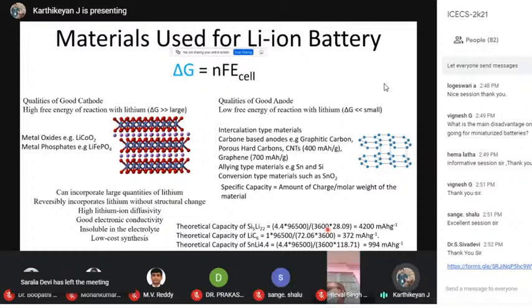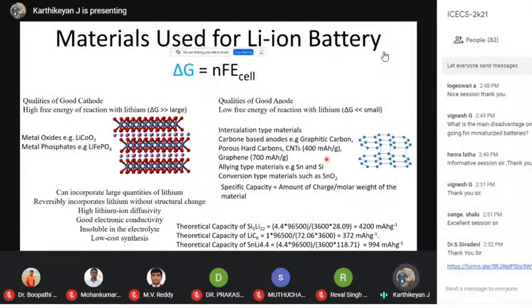Similar to silicon, we can also have tin. That is also an alloy material, but the problem with tin is again pulverization effects as well as poor interparticle connectivity. And what about other forms of carbon? Yes, carbon has other forms, like carbon nanotubes, and these carbon nanotubes have a better capacity than graphite, but again, it is not up to silicon or tin, right? Graphene has 2 times the capacity of bulk graphite, because when you take a single layer, theoretically you can store lithium on both sides. That's why the capacity of graphene is twice that of bulk graphite.